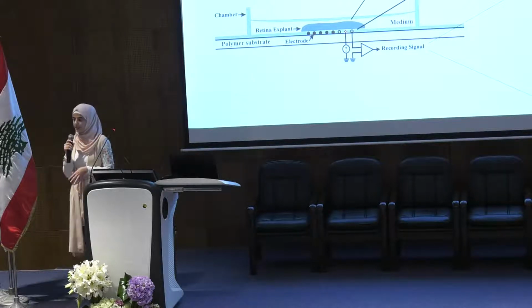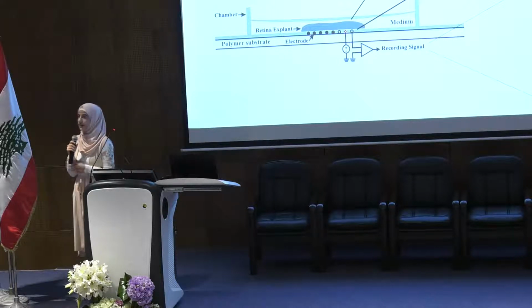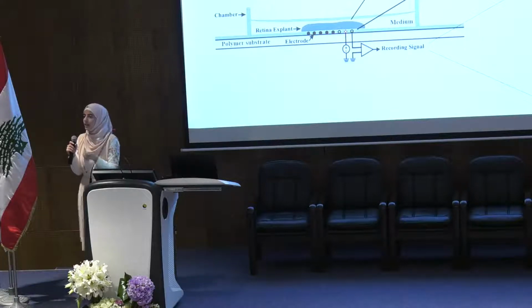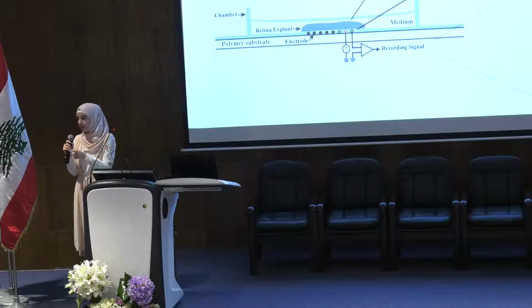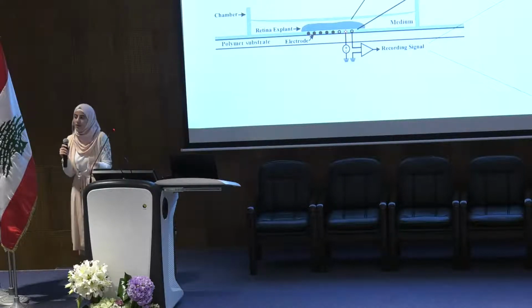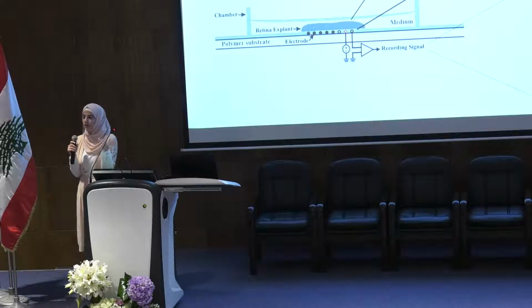They have a biodegradability rate. What we do is that we do a biodegradability test to see if the weight of the material, which is PCL, is decreasing to a certain limit, which is usually 60% of the original weight of the electrode. It means that it's not functional anymore. So when we do the biodegradability test in vitro before in vivo testing, we see the lifetime of the PCL, and therefore it depends on the overall lifetime of the device.